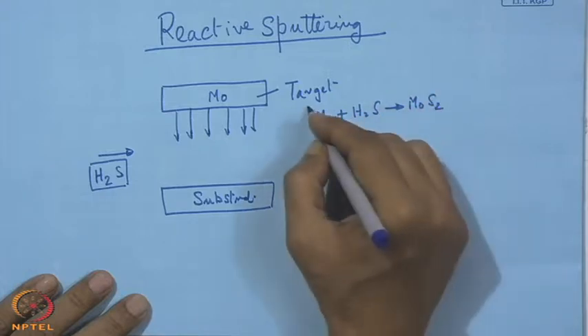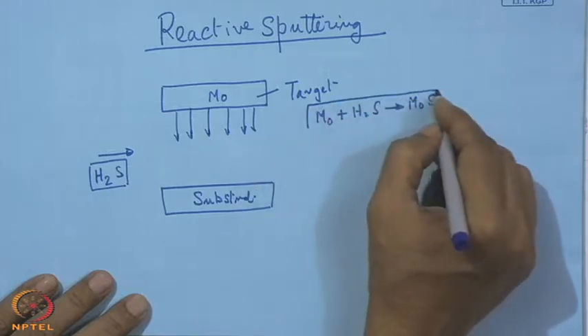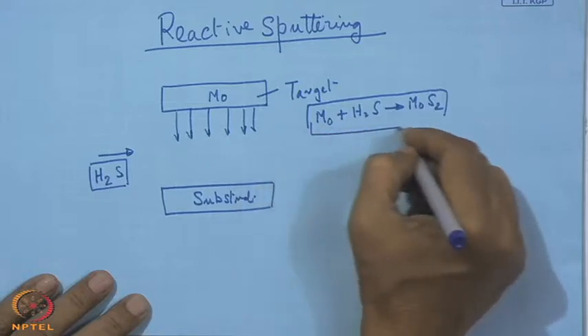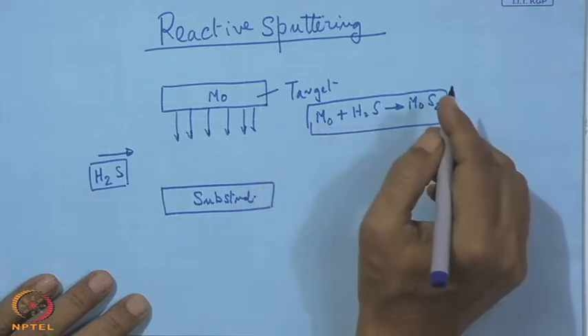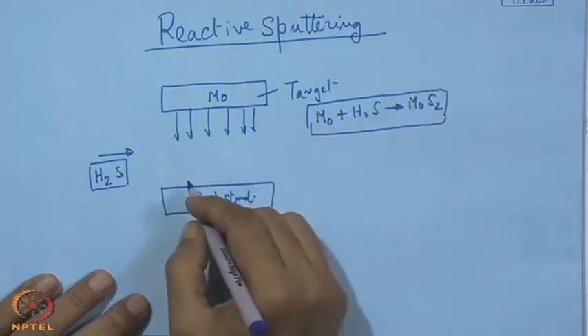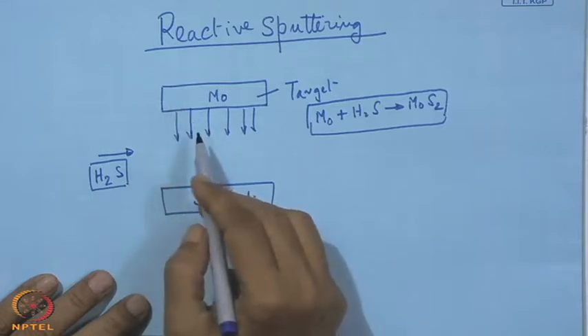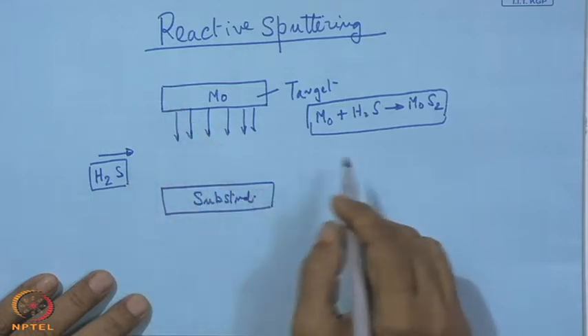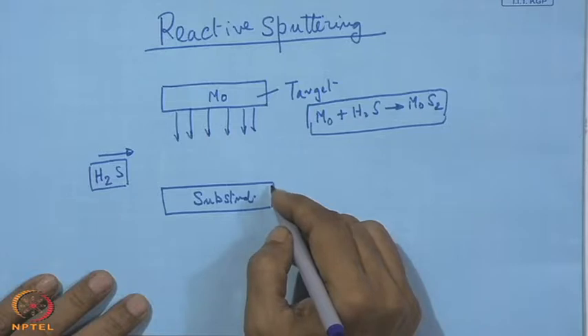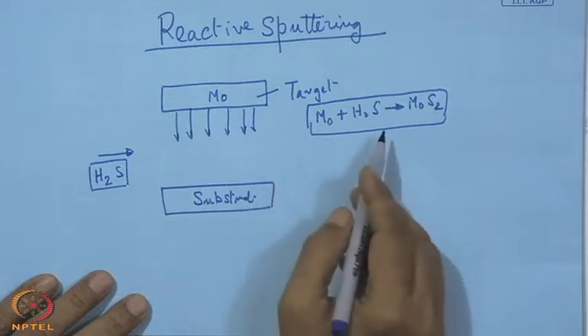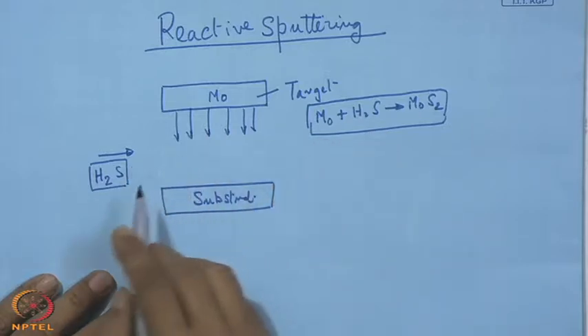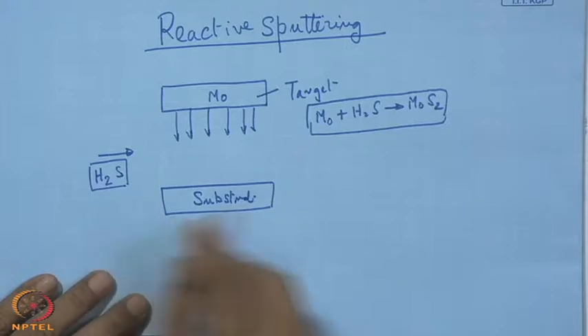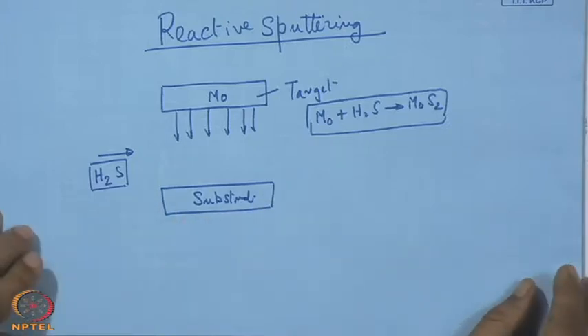This is also possible, and in that case perhaps this problem of less sulfur in the coating on the substrate, that means the deficiency in sulfur, can be eliminated by this reactive sputtering. So, that is also possible.